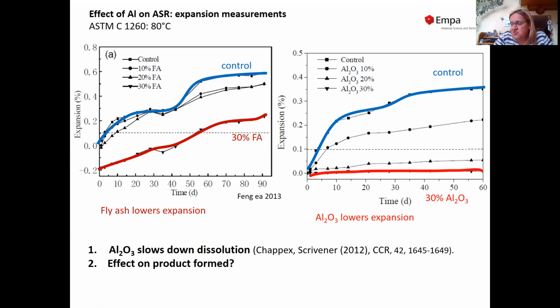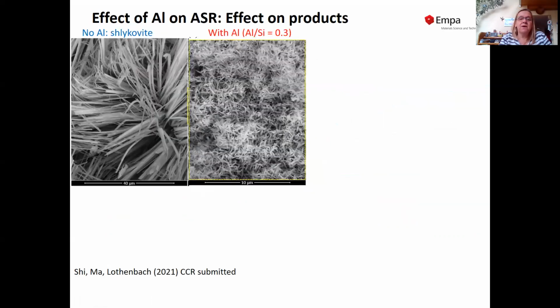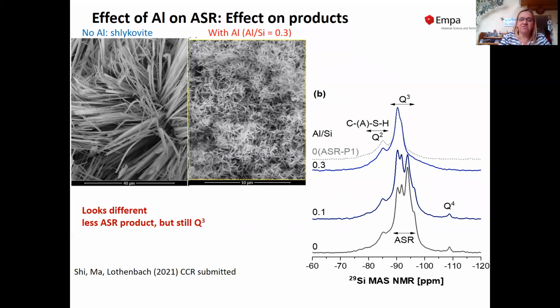Then naturally there's the question, will aluminium affect the hydrate front? We did some experiments. Again, you can see a clear difference. If we have no aluminium, we form shlykovite. If we have aluminium, we have a different morphology. We can also look at the solid state NMR data. We can see that the shlykovite we see here gets destabilized at high aluminium to silica ratio, indicating we form another solid.